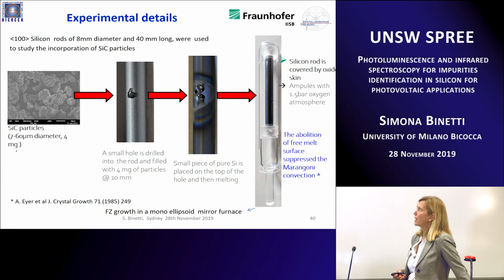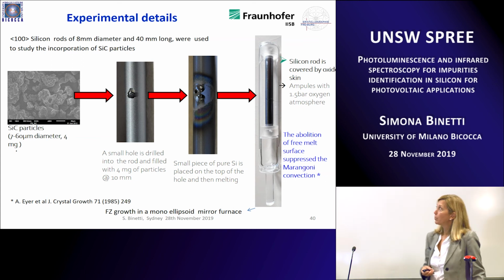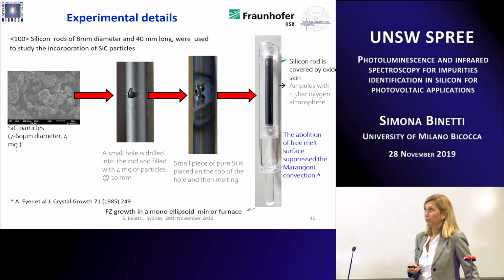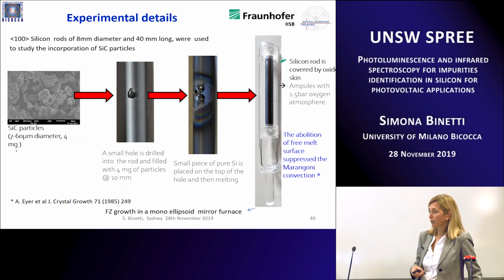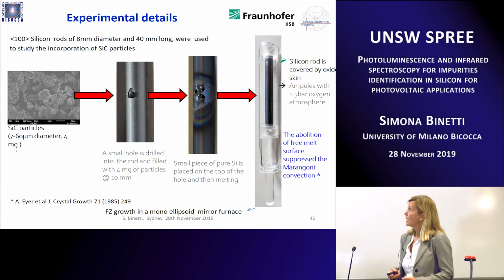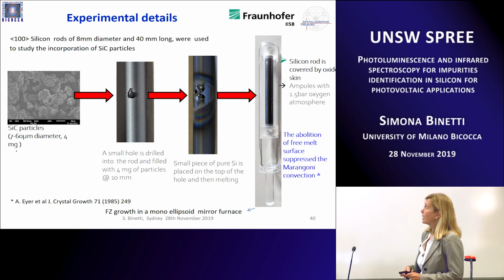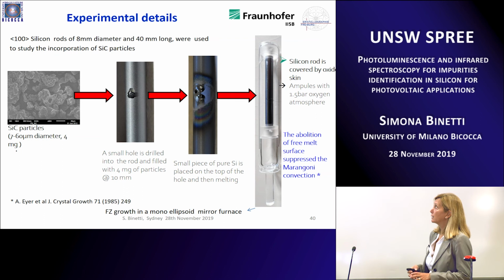So the idea was to study the movement of silicon carbide particles, which is not clear, by microgravity experiment. So they performed an ad hoc growth process, a sort of float zone growth process in which silicon carbide particles are incorporated in this ingot. Then there was the float zone solidification process, and this is made in a silicon rod that is completely